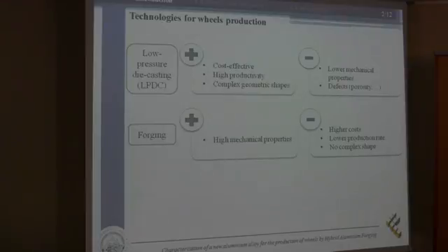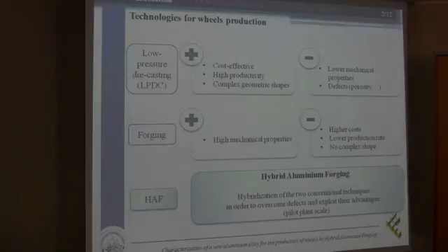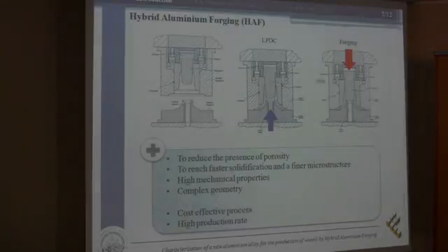production rate. So it's easy to understand how a process which can keep the advantages of these two techniques and try as much as possible to overcome the defects could be really effective and really interesting for the automotive field. This is not a new idea, and the HAF process is one of the possible processes which try to combine the two processes together in order to overcome the defects and keep the advantages. Indeed, this process mainly consists in two phases.